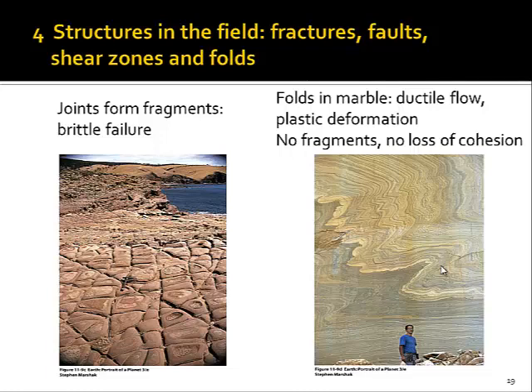If the temperature would be lower, maybe only 200 degrees, this rock would readily break and produce fractures. Such as here on this side. Here we see a rock has undergone jointing. We see here these traces of one joint set running in this direction, and another one is running straight towards us. So these are fractures in rocks, and this rock has responded to stress by breaking. And given the rock type that we see, we would assume that this rock was colder probably than 300 degrees when this jointing took place. Maybe substantially colder, 100 or 50 degrees at the time of fracturing. This does not preclude that this rock might have been at higher temperature before jointing took place, but we can bind the deformation event here to a certain low temperature at which it must have occurred.